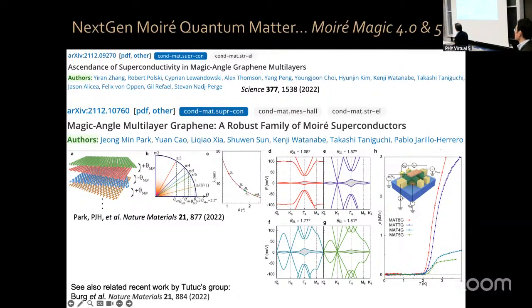Something that's interesting, I didn't have time to mention, but in a more specialized seminar I would have: this magic angle twisted bilayer, in particular the tri-layer, is the strongest known superconductor that exists. What do I mean by that? It has the highest critical temperature compared to the Fermi temperature or the density of electrons in your system. This is an extremely dilute superconductor, 1 electron or 2 every 10 nanometers.